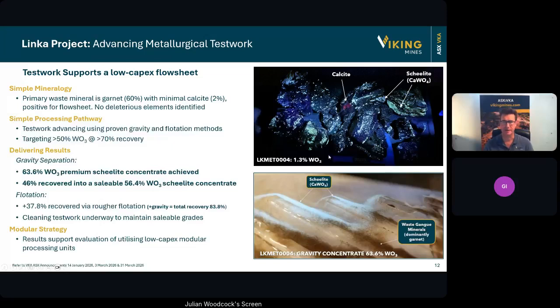Scheelite has a very unique characteristic, which means under a UV light that it fluoresces, and that's why in this image we can see all of these bright coloured speckles and zones of mineralization. So this is the scheelite that is fluorescing. There are other minerals that fluoresce here, such as calcite, but there's fortunately not very much of it. Calcite can be a problematic mineral within the flotation, and we're really pleased to identify in the mineralogical test work that we've established there is a very small amount of calcite, and the majority of the other minerals outside of the scheelite is garnet, reporting about 60%.